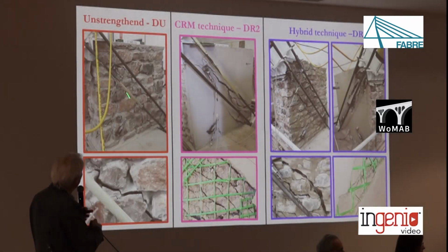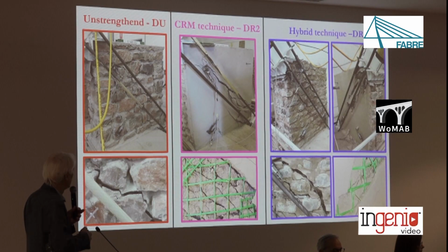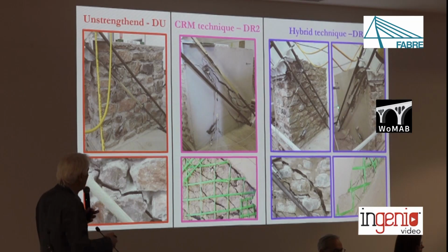Here we can also see the cracks. In the unreinforced element, the formation is of single cracks, and using this composite reinforcement we note a significant distribution of cracks.